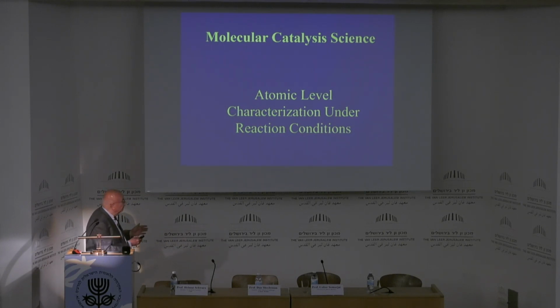Now, let's go to molecular catalysis. How catalysts work. The atomic level characterization is possible by technologies related from the synchrotron. Many of these synchrotron techniques can give you the vibrational spectrum, the composition, the size, and the scanning microscopy basically gives you the mobility of the species on the surface, and this actually, on an atomic scale, you can use under reaction conditions to see what's happening while the catalysis is running.